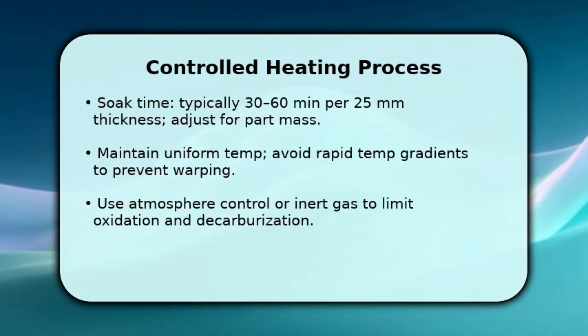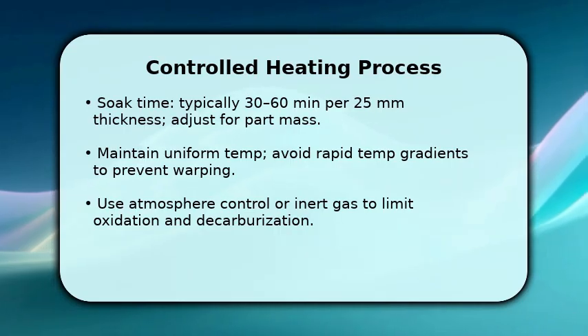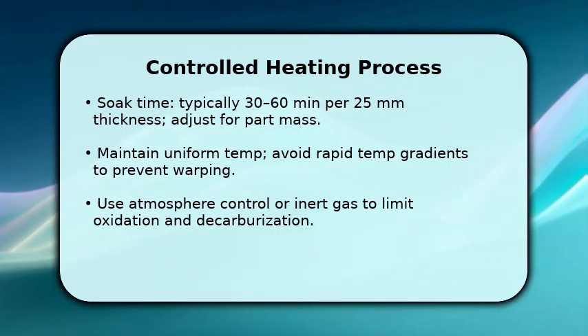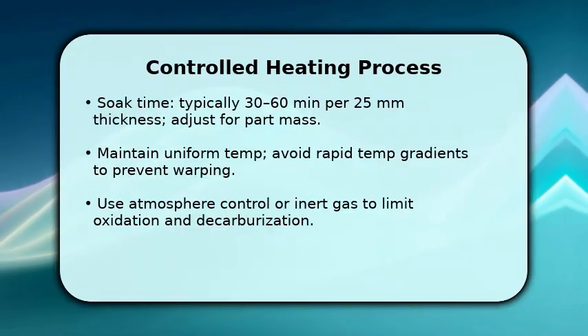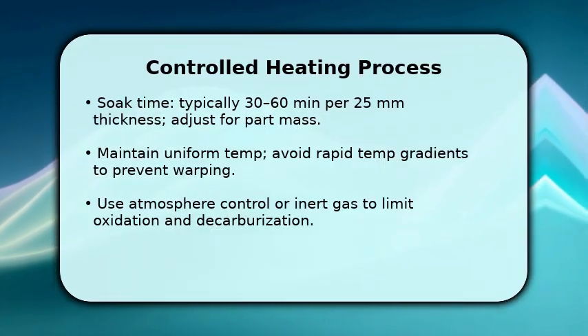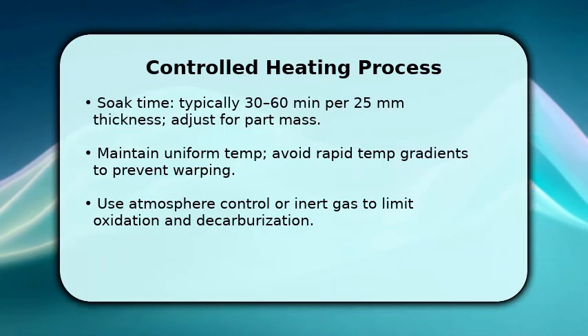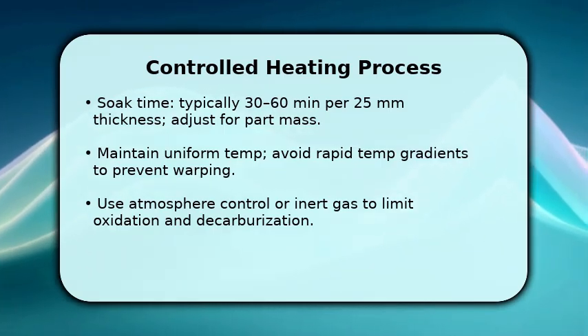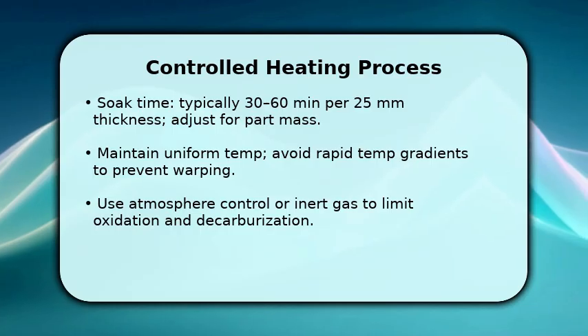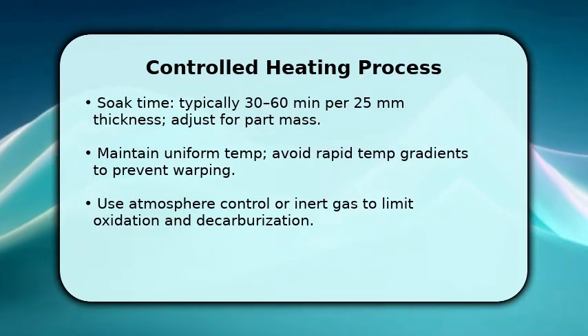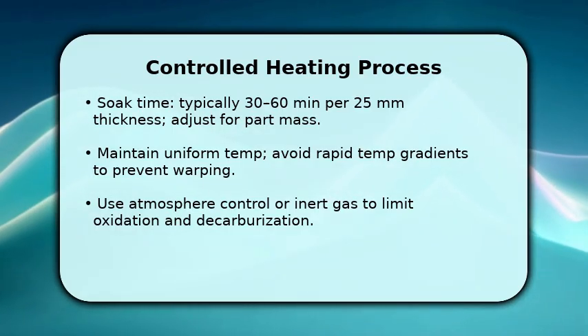You now hold temperature to let the microstructure transform. This softens the metal by reducing internal stresses. Once you reach soak, maintain it for the recommended minutes per thickness, longer for heavier sections, so grain boundary diffusion completes. Make sure to use an inert or low-oxygen atmosphere if possible, because oxidation hardens surfaces.